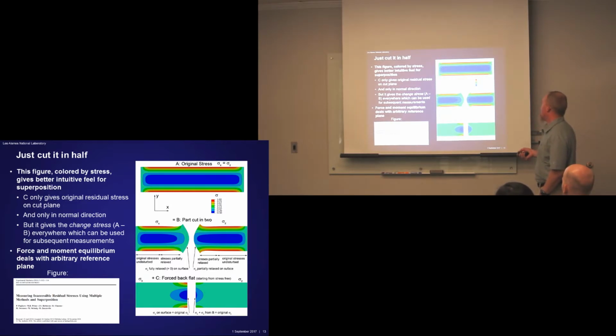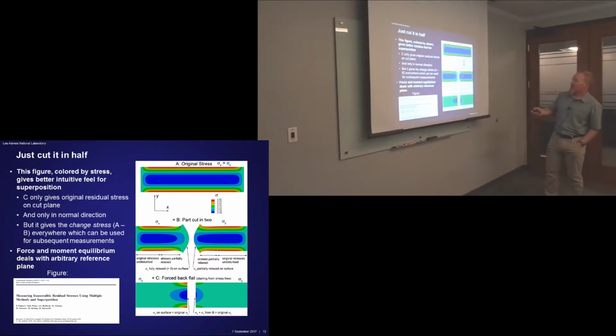And I put this figure on here, this is from a newer paper, but this is a figure of Bueckner's principle again, from an FEM simulation, just to reinforce what we're doing here. This is a model where the part has stresses X and Z, which is out of the plane, that are equal. Tension, compression, tension. You cut it in two. The normal stress on that surface goes to 0 if you look at the scale here. The Z stress, which is the out-of-plane stress, doesn't go to 0. If you measure that shape, force it back flat elastically, and add this stress state to that one, you get back that. For the other direction, the summation still works, but it's not 0 here, so you'd have to measure this as well, which is something you guys do with your, what do you call it, biaxial mapping, right? You use kind of this basic principle. It's worthwhile understanding how Bueckner's works in total.